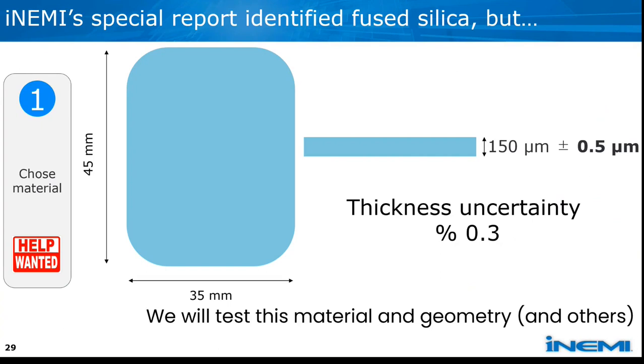So let's talk a little bit more about step one. So here, the iNEMI special report identified fused silica as a candidate for a next generation standard reference material. That's for a few reasons. One, we're able to manufacture it into this geometry, which is this rectangular coupon with the rounded edges. It's easy to manufacture in that geometry. We can also get it to have these very precise thicknesses. In this case, we've got a target thickness of about 150 microns. And we can hit total thickness uncertainties of about 0.5 microns, actually a bit better than that. About 100 nanometers, thanks to Mosaic's new processes.